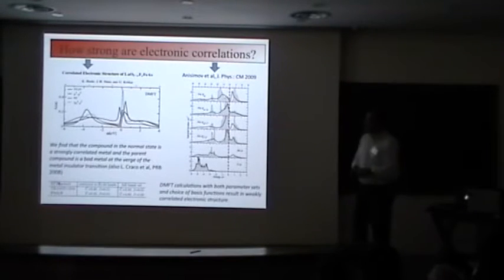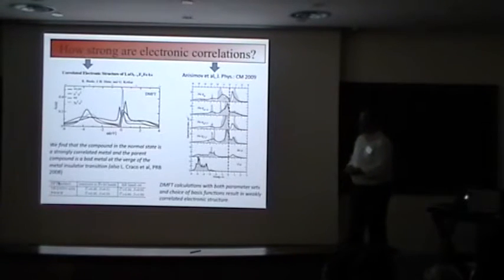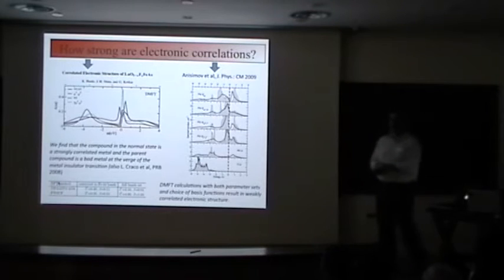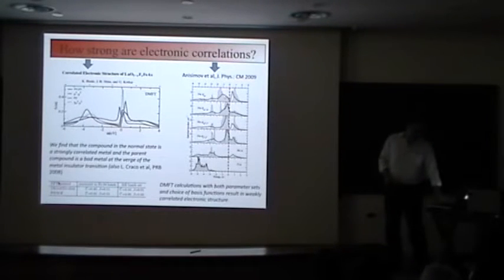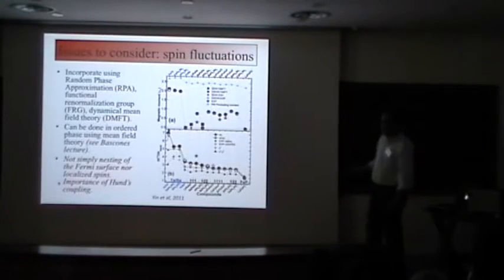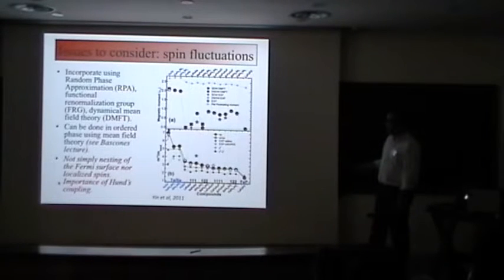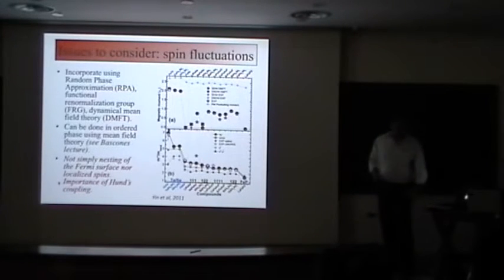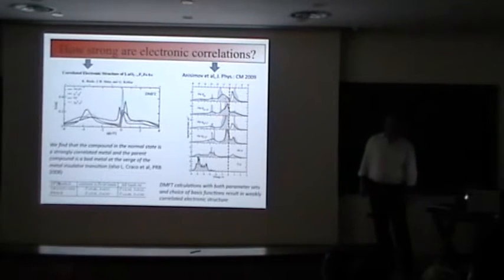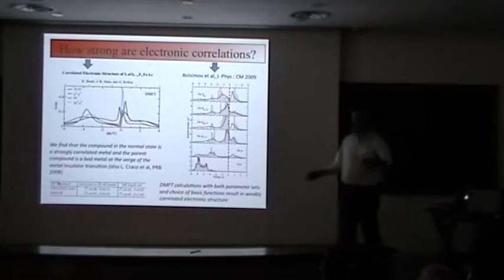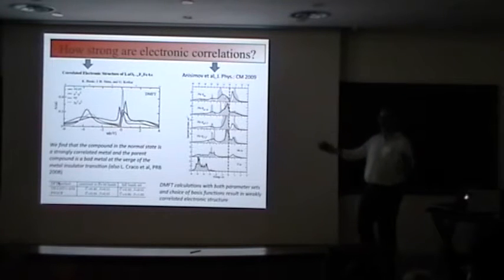So in DMFT, you could ask the question after going through the exercises, are these materials strongly correlated or not? Here you see band masses which are only a factor of 2 or 3. So you might not expect correlations to be doing all that much, but DMFT, at least at the beginning, was producing lots of different results.